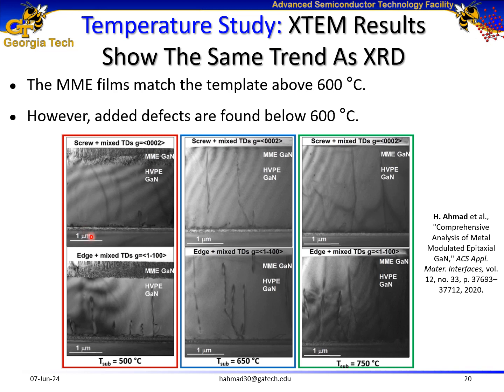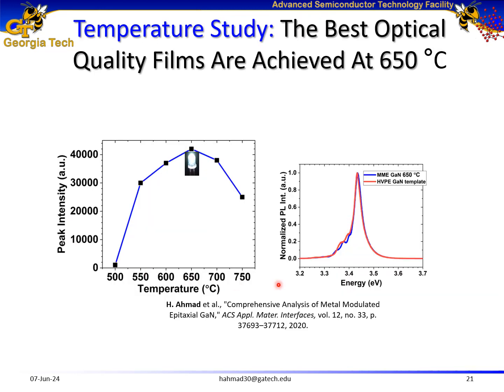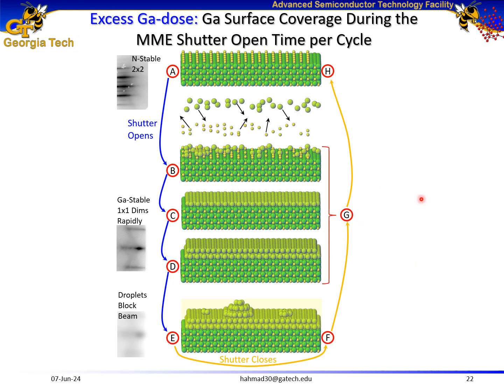Transmission electron microscopy measurements also validated the X-ray measurements, where we found that the MME films match the template quality above 600 degrees C. However, below 600 degrees C, we found added defects in the regrown films. And optical quality was found to be the best at 650 degrees C. So I fixed the substrate temperature at 650 degrees C, and now I wanted to study the effect of excess